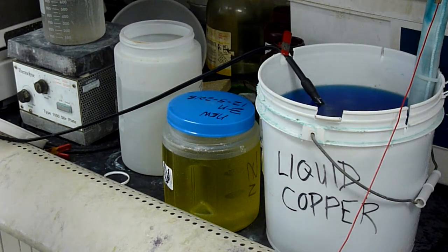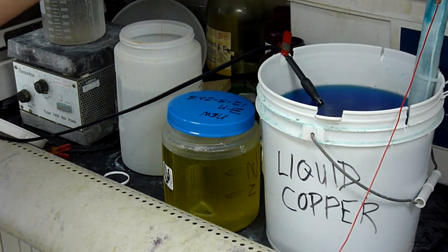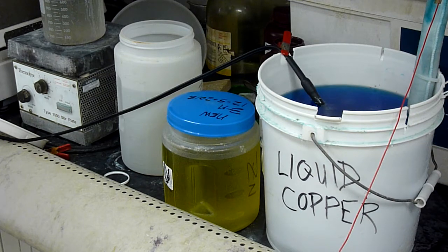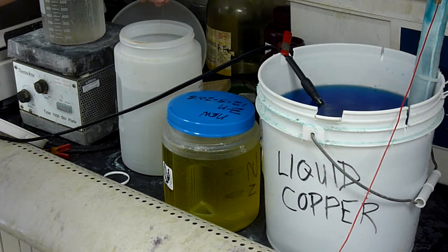But unique to when we're doing zincate plating on aluminum is a very aggressive cleaning with sodium hydroxide. We're going into a 20 or 30 percent solution of sodium hydroxide. You get bubbling immediately on the surface of the piece. I think you can see some of the bubbling action. Okay, so we come out of there.